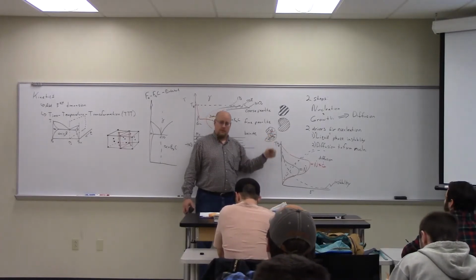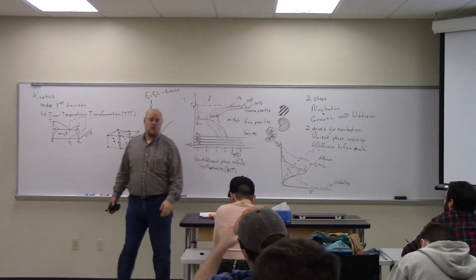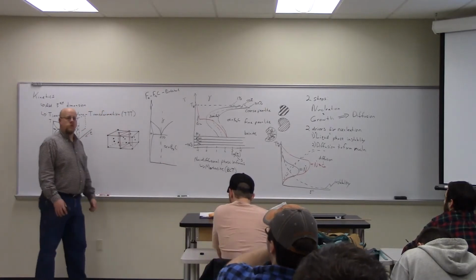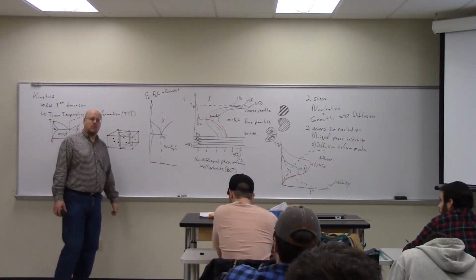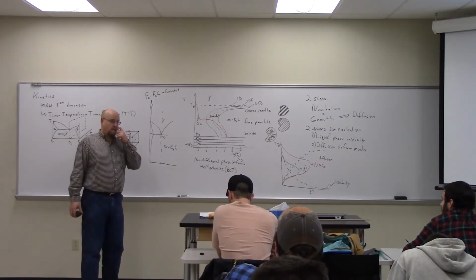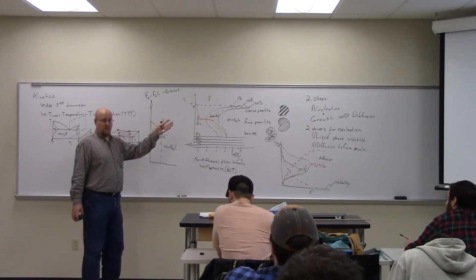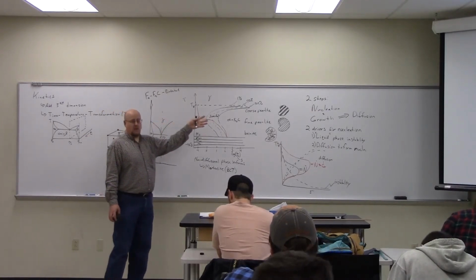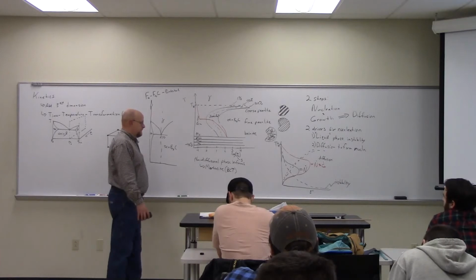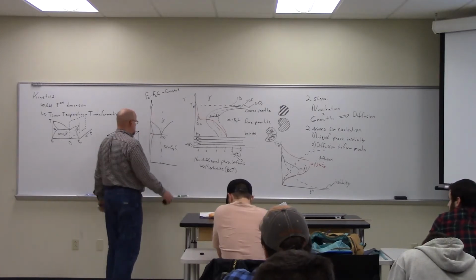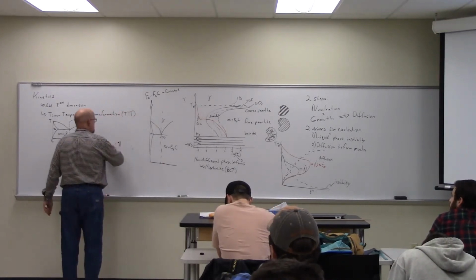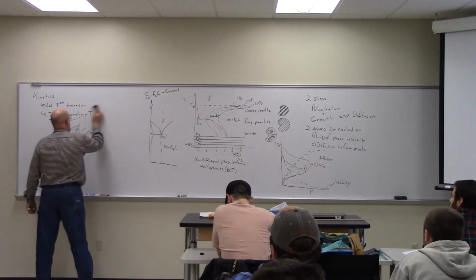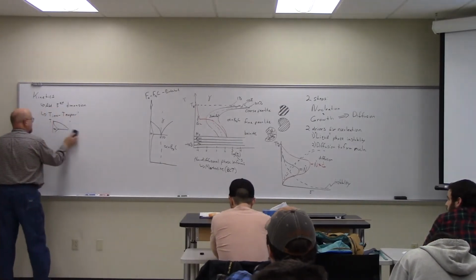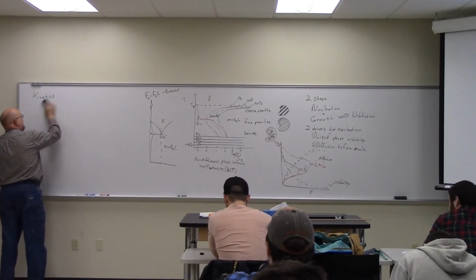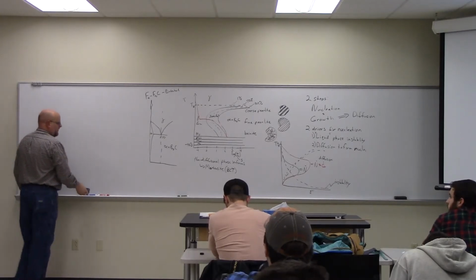So the coarse pearlite, we get over the coarse pearlite and then we just let it slowly cool after that. It's going to be fairly soft. Pearlite? Right, yeah. There's no driving force to form anything else because it's perfectly at equilibrium with alpha and Fe3C. And then it'll become martensite? No, it won't become martensite. Once it's formed alpha plus Fe3C, there's no more martensitic transformation.